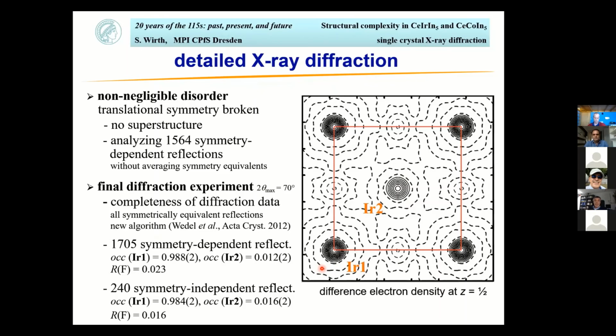So they did a very nice experiment here, keeping all the 1705 symmetry dependent reflections. And what you get by fitting is that you have 98.8% of the iridium in the, let's call it, regular position, but then you have this additional structure pattern with about 1.2%. If you consider the symmetry independent reflections, meaning you average over the reflections, then you get something like 1.6% for this additional structural pattern. So it's pretty close to each other. So you pick your choice. I would say something like 1.5% of this additional pattern is seen.